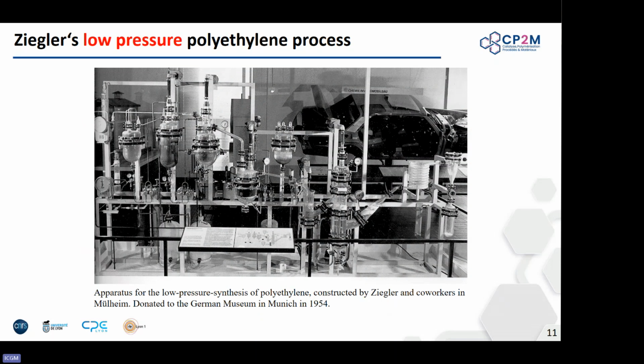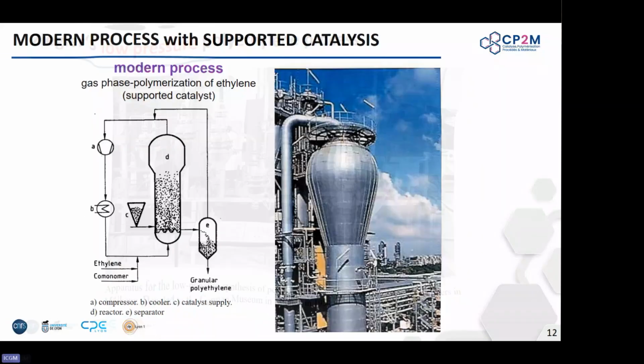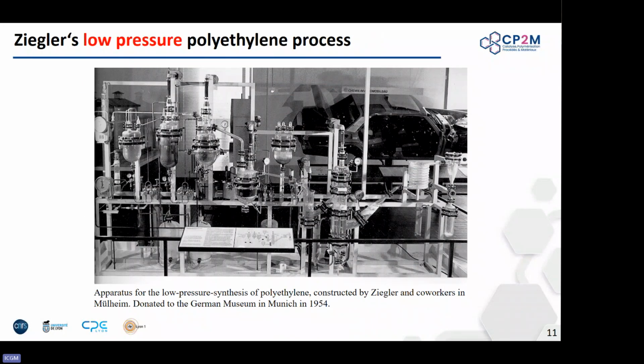So this is the first actual polymerization of ethylene unit. It's a historical thing. You can see a lot of glass reactors, and there is a separation of the polymer because, okay, the catalyst loadings were really, really high at that stage, okay? It was not supported catalysis. It was a kind of starting as a homogeneous mixture, and then the polymer starts to precipitate and crystallize. Therefore, you have to somewhat separate the excess titanium that you have on your polymer at the end. Okay, so these are separation steps.